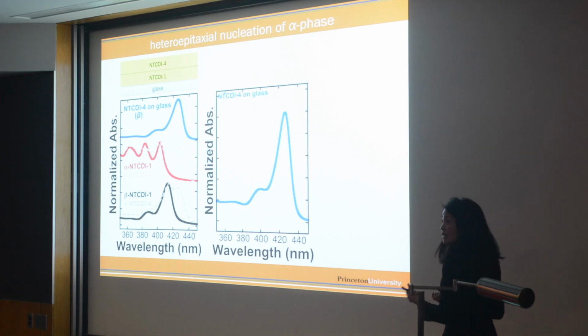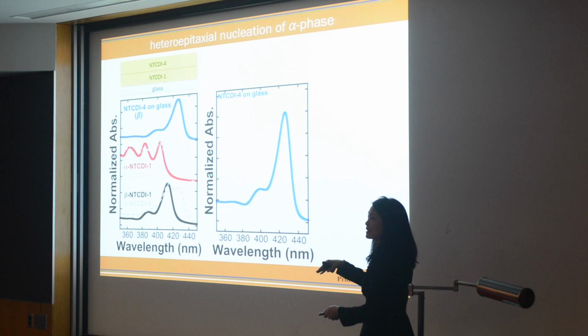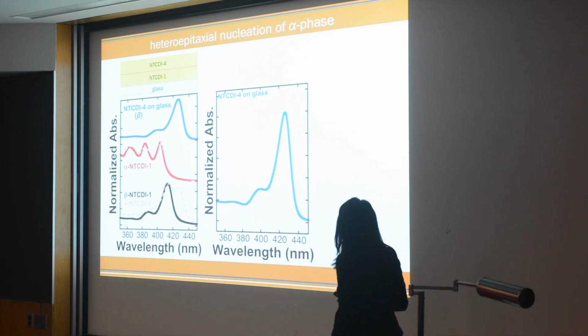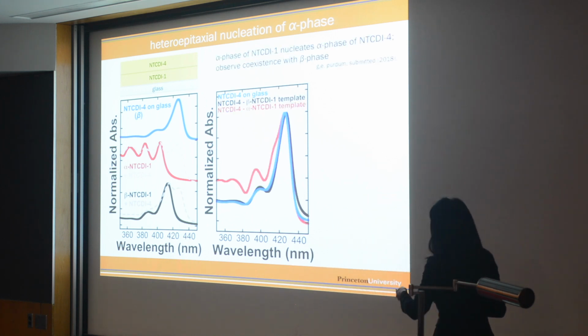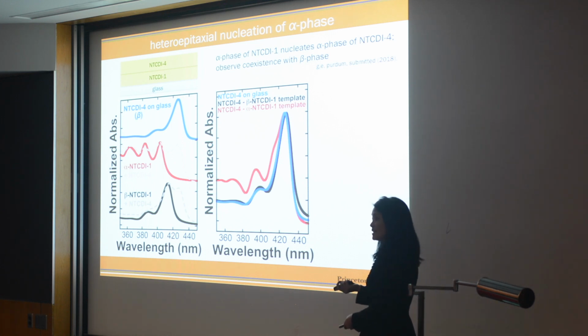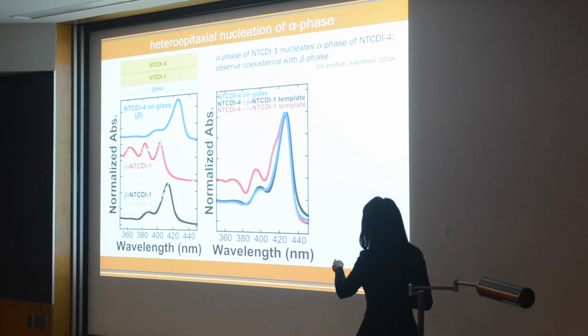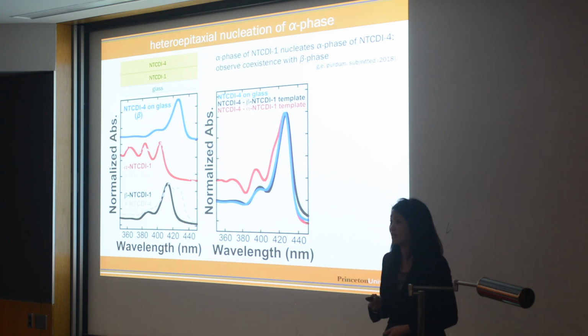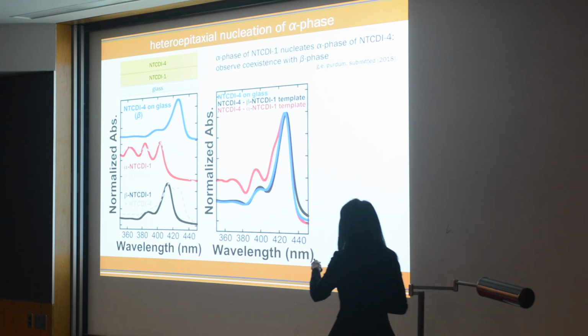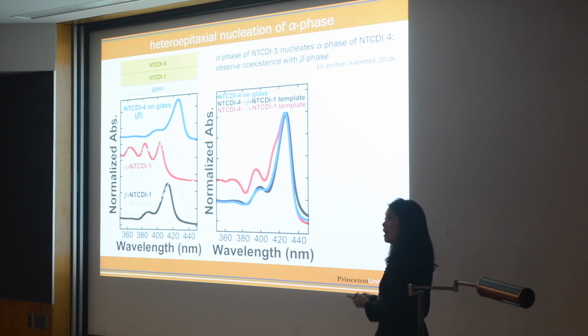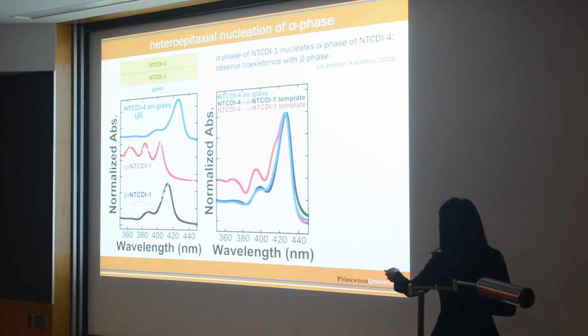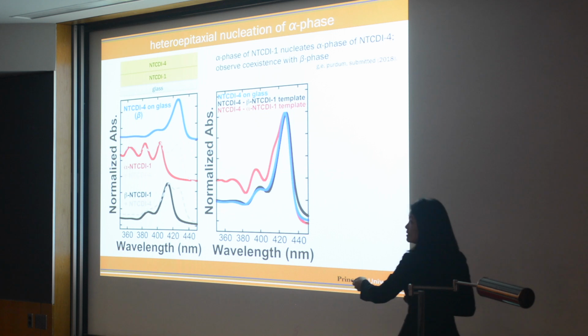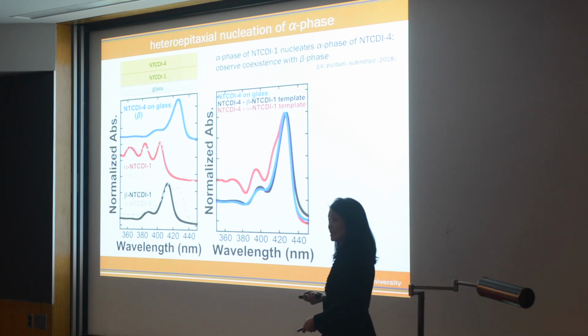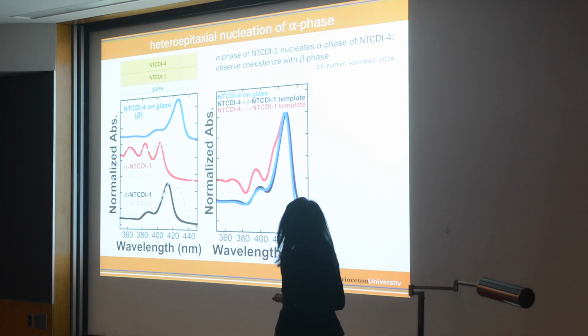So what we did was we collected the difference spectrum, right? So you subtract the signal from the bottom. And when you do that subtraction, you can see it clearly. So if you deposit NTCDI4 on the beta phase of NTCDI1, that data is shown in black, and that data is similar to the blue data, telling us all we have is beta NTCDI4. Now, if you take NTCDI4 and you deposit it on alpha NTCDI1, that data is shown in red, and you see extra absorbance. And that extra absorbance is associated with the alpha phase of NTCDI4.